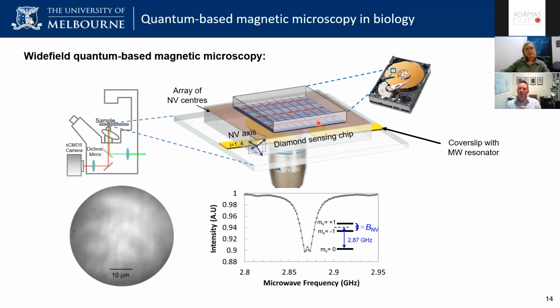When you're doing T1 imaging, that relies on the exchange of magnetic dipoles, and that has a dependence that goes as 1/R^6. So T1 is extremely sensitive to the standoff between the NV layer and the sample that you're interested in. The closer the implant can be to the surface for T1 sensing, the better. That's where we would win a lot in terms of our sensitivity to measuring fluctuating magnetic fields.